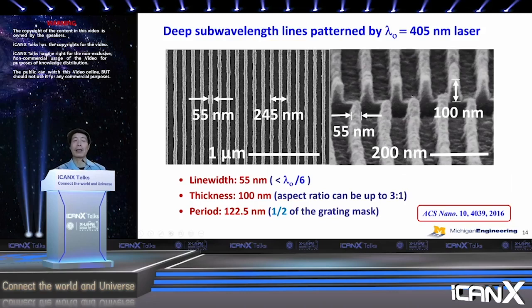Okay? One other problem here is that the period of the pattern is one half of the period on the mask. The period on the mask is 245 nanometer, which is still very small. In our case, you have to use electron beam lithography to pattern it. So that's still a limitation. We want to address that problem as well. We want the mask to be much bigger, so you can do it with photolithography.